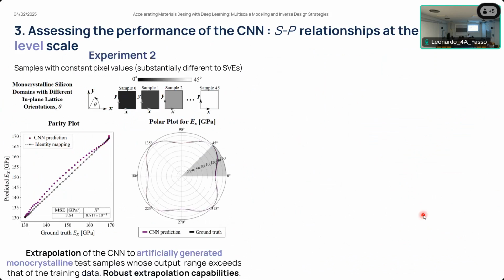The second experiment to evaluate the extrapolation capability of the deep learning model is one where we assemble a small test set of samples that are displaying constant pixel values. These samples, as you can see, are significantly different than the ones that were used for training the neural network. And in this case, what we want to understand is if the CNN is capable to provide accurate predictions and capture the nonlinear relationship between the lattice orientation of monocrystalline domains and the effective property associated to the Young modulus. We obtained very good agreement in the predictions with an average relative error lower than 1.5%.